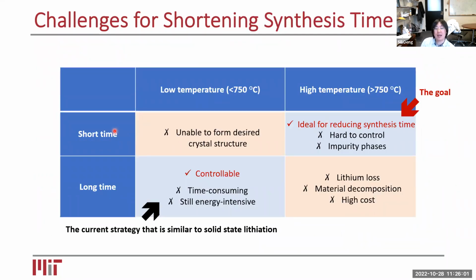Now we think about why we need the annealing. Like I mentioned, we need to achieve a certain crystal size, and we need to achieve a uniform distribution of elements. And this basically constrains us into these two corners, right? The industry utilizes this method where we use relatively low temperature and long time so that the process is slow enough that we can control it. Of course, the downside is you need a long time, so it's very energy intensive. You need workers to be there, you need things to run for a very, very long time.